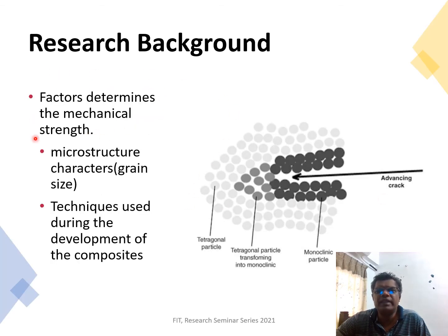So what determines the mechanical strength? Of course, the grain size. How big is the grain size? The smaller the grain size, the more probably it will be in the form of tetragonal phase, a very stable phase. Research found that more tetragonal phase means higher mechanical strength. So smaller microstructure, better mechanical strength. And second, what determines the mechanical strength is the technique used to develop the composite, like what techniques are used to minimize the size of the grain.